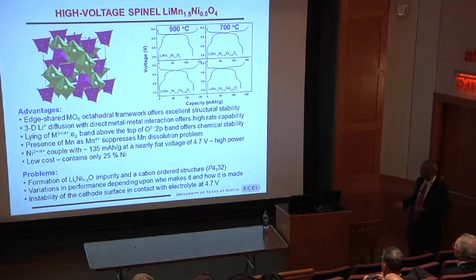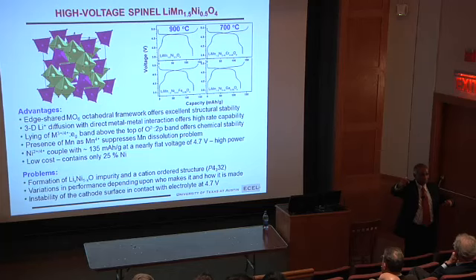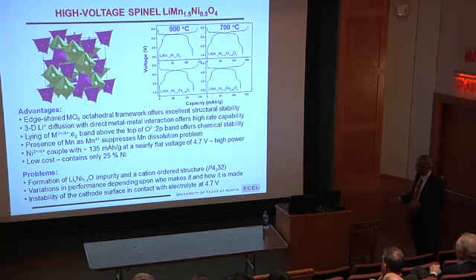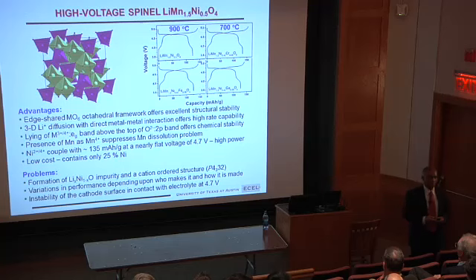The issues are when you form it, you get nickel oxide impurity. Not all the nickel is in the lattice. And it also tends to order in the spinel lattice because manganese 4+, nickel 2+, big charge difference and big size difference. So they tend to order. When they order, electronic conductivity goes down. So that's one issue. Because of that, the material performance varies a lot depending upon who made it in my lab and how it was made.